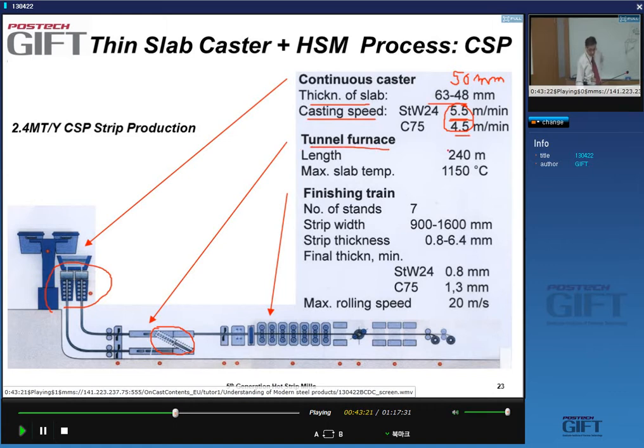The tunnel furnace, 240 meters, of which a considerable part of the length is a swivel furnace, yes, as you can see here. The slab, or bar temperature is 1150 typically in this case. And the finishing typically 5 to 7 stands, in this case you have 7, yeah. And the width 1600. Now strip thickness, and this is important, yes, is a